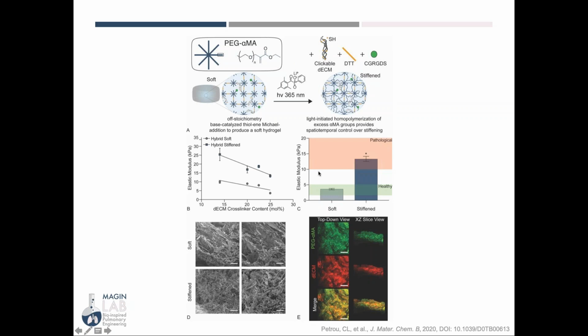And we've been able to tune our materials so that we could create a dual stage polymerization where our first material is cross-linked in a Michael addition off stoichiometry to create a soft material. And then we add a photoinitiator, initiate a homopolymerization of the remaining methacrylates, and create a stiffening event that stiffens our material into the pathological range. So you can see from our confocal images that if we label the PEG and the dECM, we get a good mixture of both components.